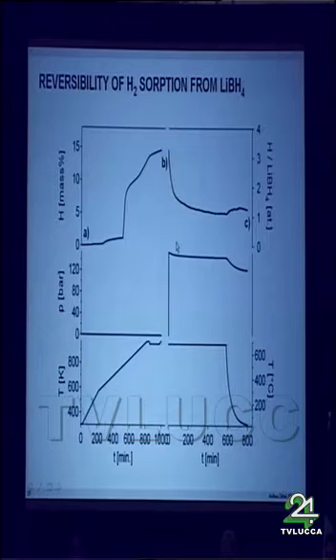The more important open question with borohydrides is the reversibility, and that's an experiment we did on lithium boron hydride. Here is first we increased the temperature, we desorbed the hydrogen. You can see that here we desorbed 3 of the 4 hydrogen, and then we applied a high hydrogen pressure and reduced the temperature, and we reabsorbed the hydrogen.